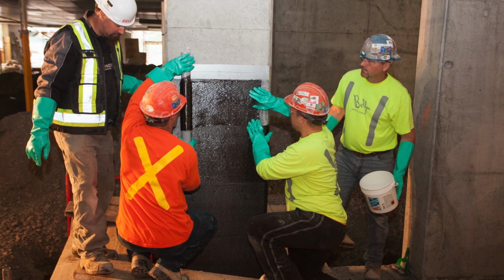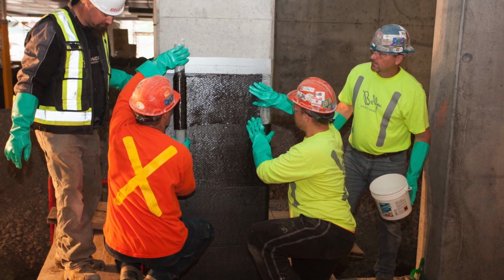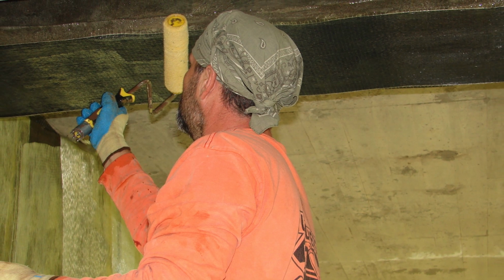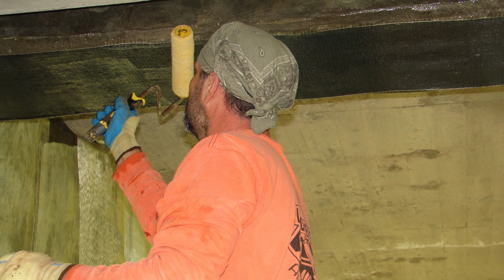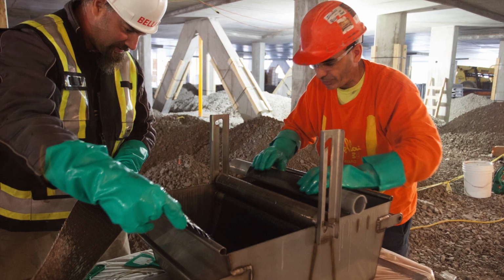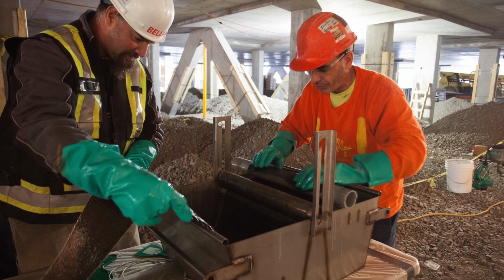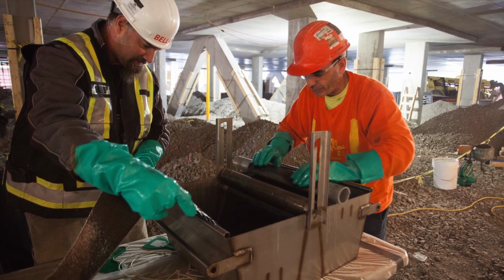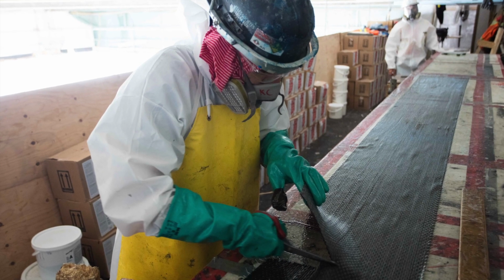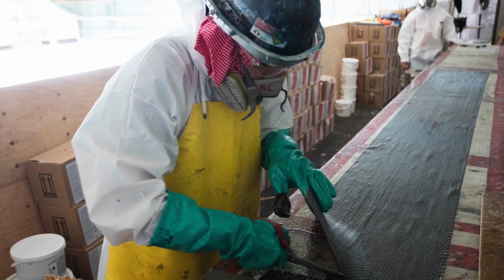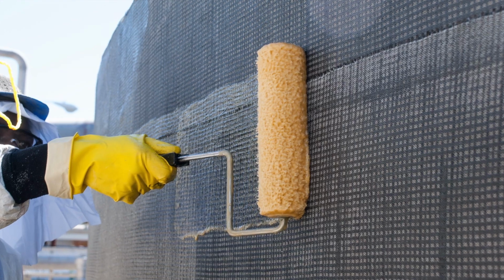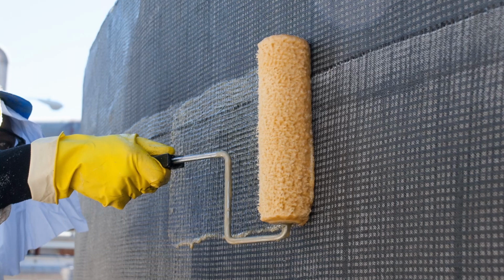MapeWrap 21 is a low-viscosity 100% solids epoxy saturant specifically designed to wet out fibers. It can be used with manual or automatic saturation equipment. Once mixed, MapeWrap 21 will allow 20 to 60 minutes of working time in a temperature range of 50 to 86 degrees Fahrenheit or 10 to 30 degrees Celsius.